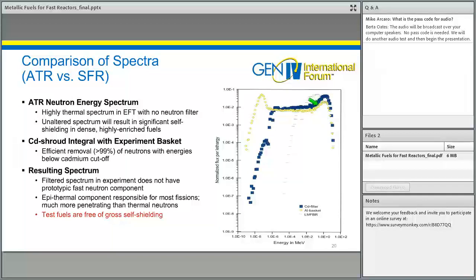So you have your high energy fission spectrum, a lot of epithermal neutrons associated with slowing down, and then a large thermal peak. This would be a neutron energy spectrum entirely unacceptable for testing these fast reactor fuels. And so what we've done is we've built into our test vehicle a cadmium shroud. So the rodlets are entirely shrouded by cadmium. And this dramatically alters the spectrum that the test fuels see.